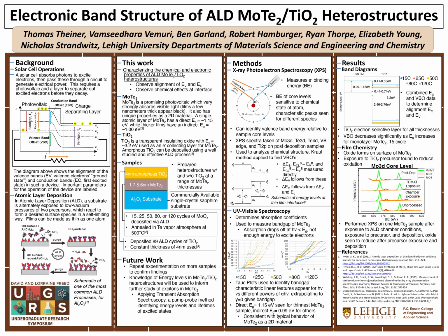This tells you where the different core levels of electrons are, and also even out to the edge of the valence band. And this is useful because this is precise enough that different chemical species have distinct binding energies, because the bonding character changes slightly, and this changes how tightly electrons are held. And you can measure all the way out into the valence band, and that'll tell you the energy of the edge of the valence band relative to the core levels of the sample.